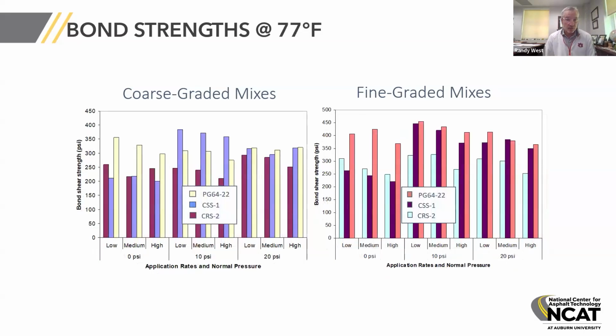At 77 degrees, we did see more of an effect of the binder or the tack coat material for coarse graded and fine graded mixes. But generally, in most cases, the PG binder was among the best, not always the best, but generally among the best tack coat materials in this experiment.